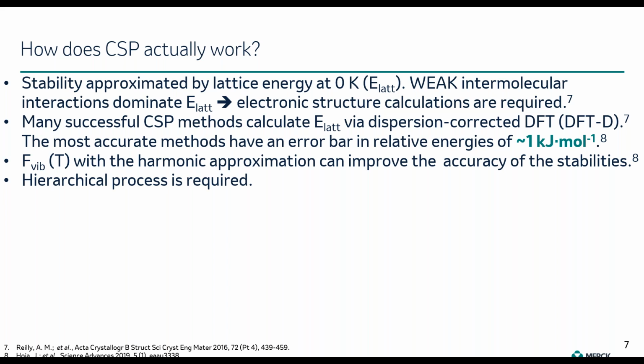Lattice energy is dominated by weak intermolecular interactions, and so an accurate assessment requires costly electronic structure calculations. There are many successful CSP methods, and several of them calculate lattice energy via dispersion-corrected density functional theory. And the most accurate dispersion-corrected density functional theory methods have a relatively low error bar in the relative rankings of predicted forms of approximately 1 kilojoule per mole. On top of calculating lattice energy, the addition of the vibrational component to free energy at finite temperature, calculated with the harmonic approximation, has been shown in the literature to improve the accuracy of the predicted stabilities relative to experimental data.